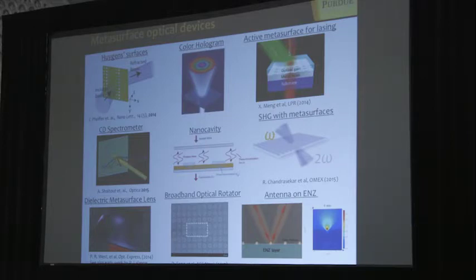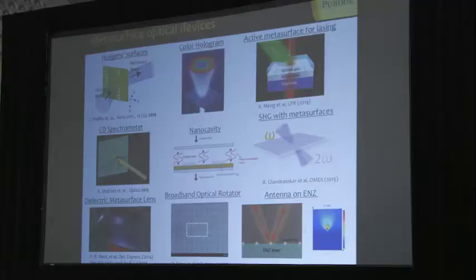Normally, if you place antenna on a substrate with large refractive index, most of light actually goes to the substrate. However, if you put it in ENZ, epsilon near zero materials, because of a huge impedance mismatch, all the light goes up. And there are also very interesting pinning effect. It turns out that you could completely change the way antenna radiates by using these metasurfaces.